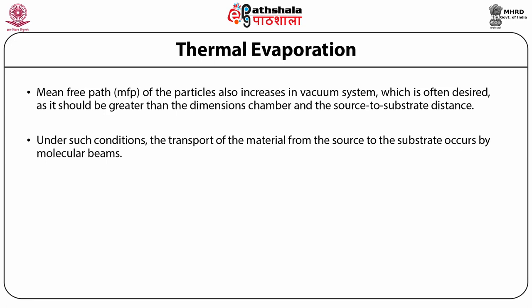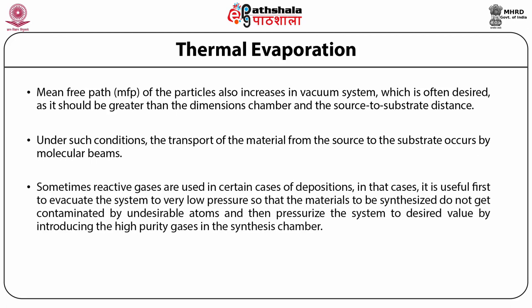Under such conditions, the transport of the material from the source to the substrate occurs by molecular beams. Sometimes, reactive gases are used in certain cases of deposition. In those cases, it is useful first to evacuate the system to very low pressure so that the materials to be synthesized do not get contaminated by undesirable atoms, and then pressurize the system to the desired value by introducing high purity gases into the synthesis chamber.